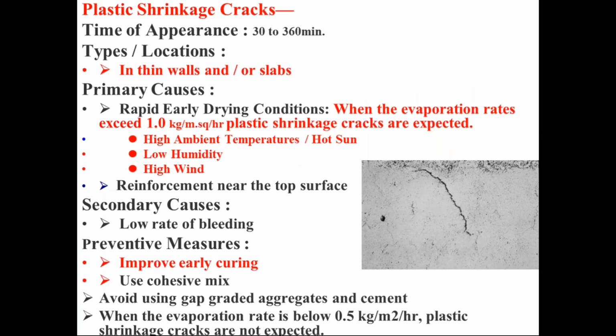By putting plastic sheet on the surface of the slab which is cast, which gives a protection, and the water, if it is trying to come out, gets condensed on the plastic sheet and protects the concrete from future drying. Use of cohesive mix, avoiding gap graded aggregates and gap graded cement, and controlling the evaporation rate, which is not in your hands completely, to 0.5 kg per square meter per hour, plastic shrinkage cracks can be avoided.